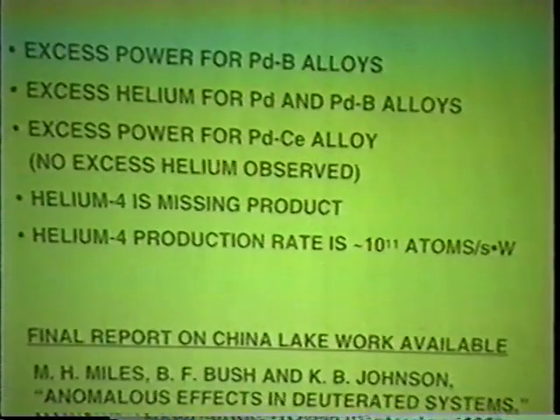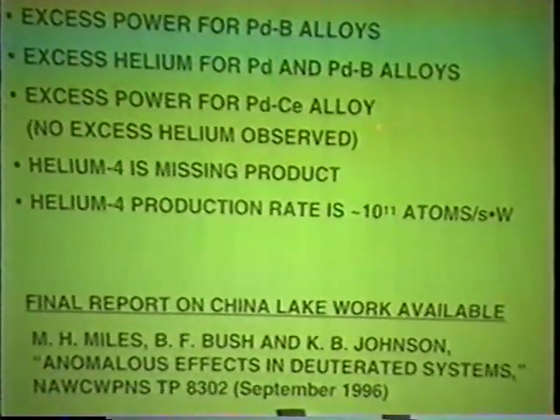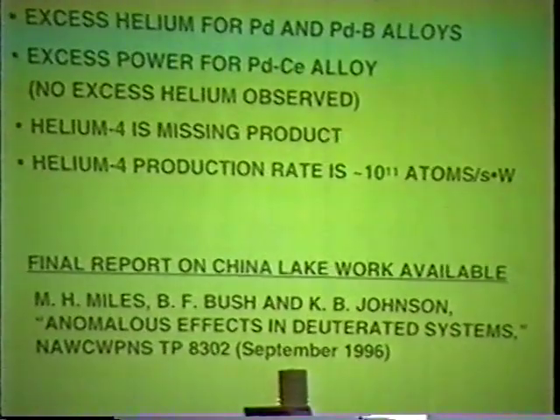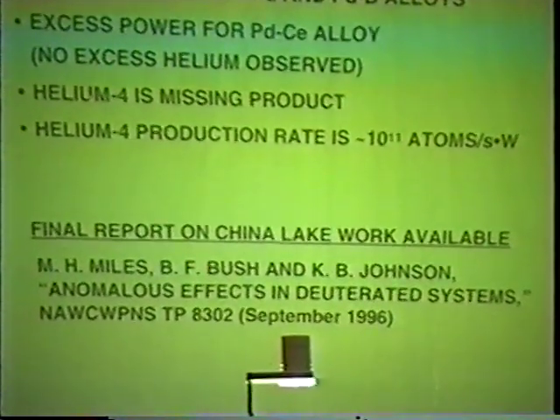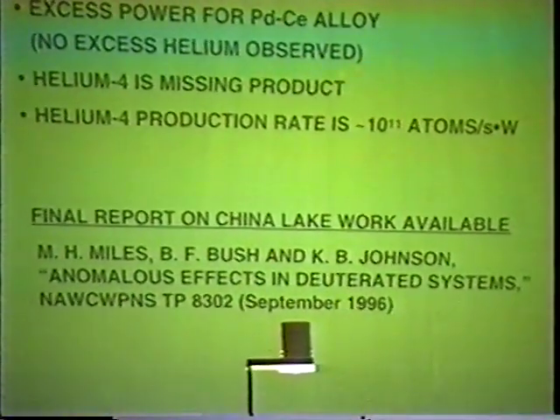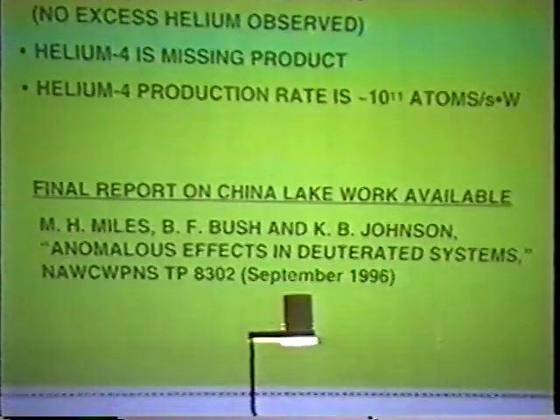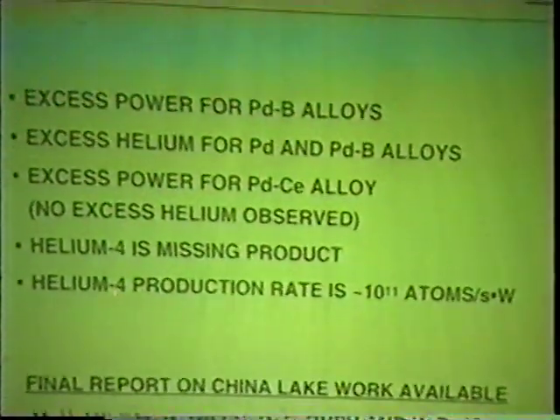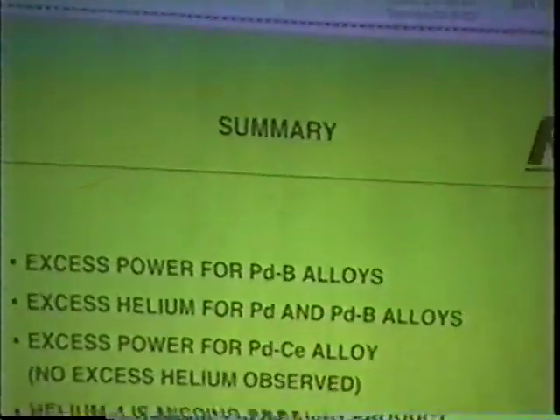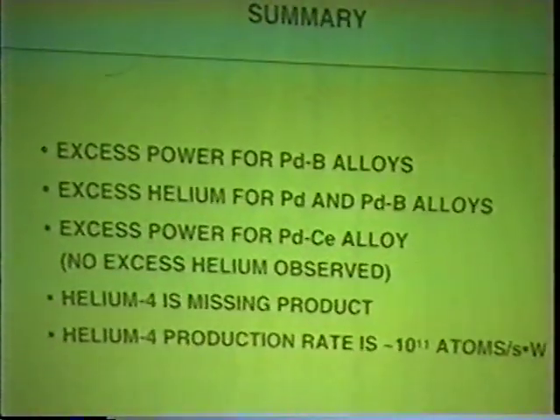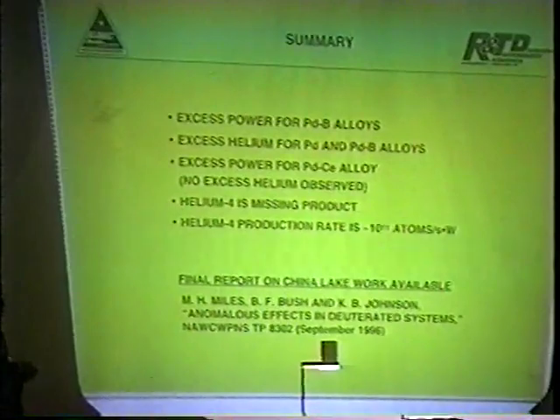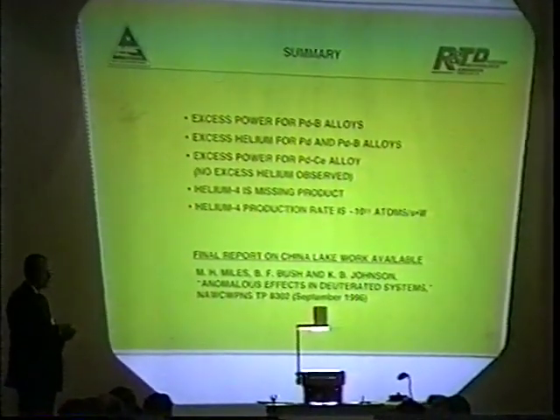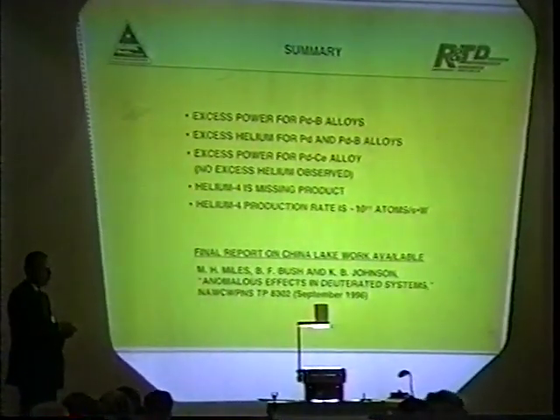This is two of the 33 studies where we did not get a correlation. But based on our results, we feel helium-4 is a missing product. It is a product of the reaction. In all our experiments where we found helium-4, the helium-4 production rate always comes out very close to 10 to the 11 atoms per second per watt, which is about the right order of magnitude.